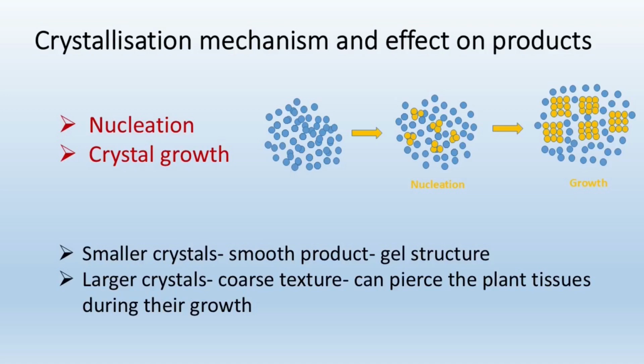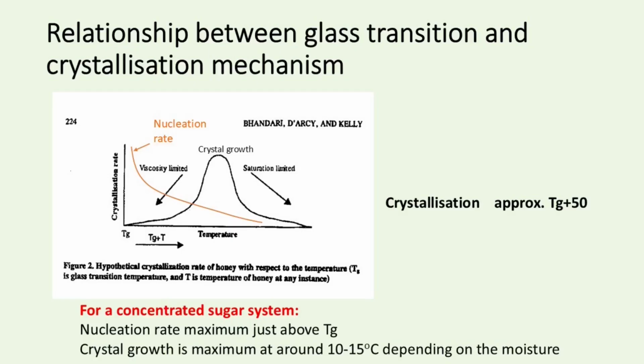If you get very small crystals, you get a smooth product, jelly structure, and you don't see any crystals on the surface. If you have large crystals, then only you observe them. So why is it happening? These are the things we have to understand. And then we try to relate glass transition and crystallization, nucleation and crystal growth, at different temperatures. Nucleation is very fast and closer to the glass transition temperature, and crystal growth is away from the glass transition temperature because of the changes in molecular mobility.